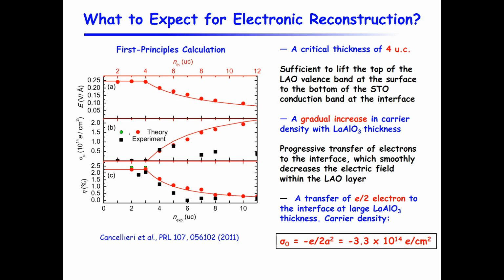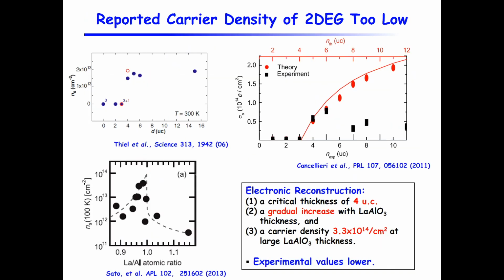The critical thickness has been observed by many, many groups. But this gradual increase has never been observed by any group. And many groups have the problem that this number is not right. That's what I'm showing on this slide: the reported carrier densities in the literature are too small. And this work, for example, has this abrupt change to something like 2 times 10 to the 13th. This is again the slide that I showed earlier. This is what is predicted by theory, but these are the data points that people got from the experiment.